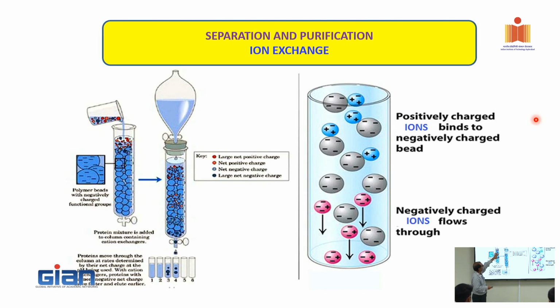We actually have the leach liquor here, and in a column, this is packed with the resin. Once you pass the liquor through this, the exchange reaction takes place. This is called loading. And the solution which you are getting out is a barren solution, right? Once it is loaded, you have to elute it, because ultimately you have to recover it. So you have to elute it with a different solution called eluent.